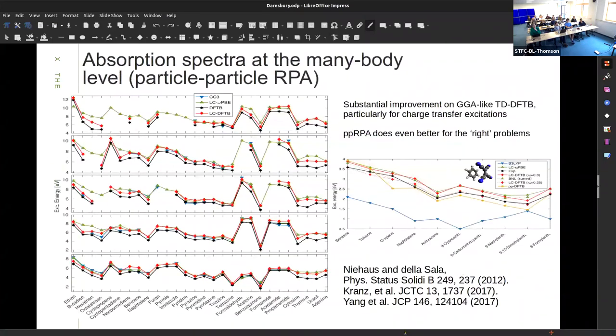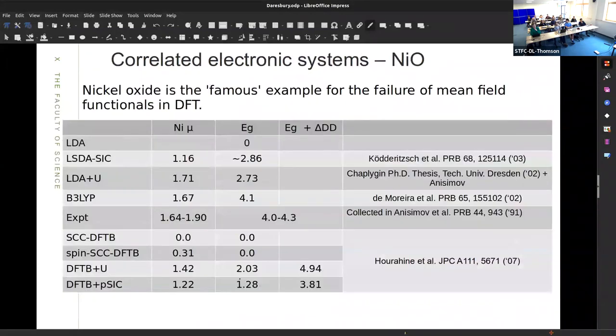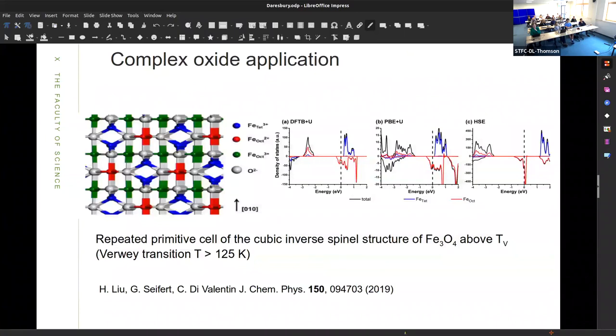There are also many-body excitations — things like particle-particle RPA, a good way to get collective behaviors into excitonic systems. For correlated systems such as nickel oxide, there's a whole family of methods based on what was originally LDA+U, adapted into DFTB. This can be applied to complex oxide systems — for example, a paper with Gotthard Seifert looking at iron oxide systems above a structural phase transition, where the density of states is qualitatively similar to DFT choices, but fast enough to explore multiple alternative structures much more efficiently.